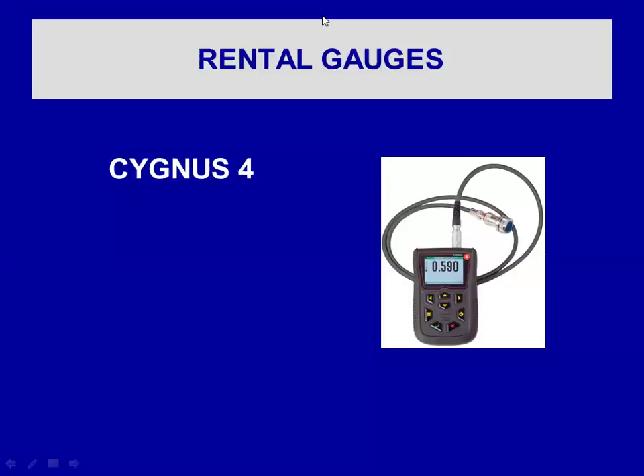So the whole idea is that we have gauges from simple thickness testing to, depending on the level of specification or the depth of the inspection program, more. Do you want just a basic gauge, or do you want that in case you get corrosion, if you want to measure around the corrosion? You can take a thickness gauge and work your way around it, you can knock it down with a hammer, and you will surely find some parallel walls in there. You can surely get some real thickness measurements. Is that enough information? If it's not enough information, put the thickness gauge away.